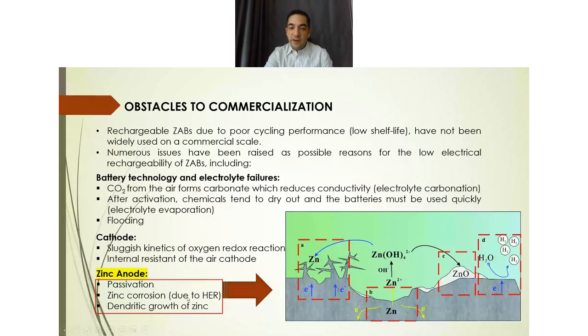This graph shows very clearly how these three issues affect the surface morphology of the zinc anode. Here on the left, this is the growth of dendrite, and in the center is the shape change of the battery that can occur during cycling, and on the right side, it is the zinc oxide that has been deposited on the surface and passivates the surface. And on the last bar, you can see how hydrogen can corrode the zinc.